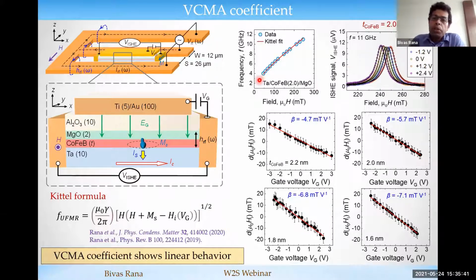Then we plot the frequency as a function of electric field, and by using the Kittel formula, which gives the relation between resonance frequency, the bias magnetic field and the perpendicular anisotropy, you can extract the value of perpendicular anisotropy for various gate voltages, which we have plotted here. So we systematically measured the variation of perpendicular anisotropy as a function of gate voltage for different values of cobalt iron boron thickness, varying from 2 nanometers down to 1.6 nanometers. In all the cases, you can see the perpendicular anisotropy varies linearly with the gate voltage. So we didn't see any kind of nonlinear behavior of this VCMA in our system.